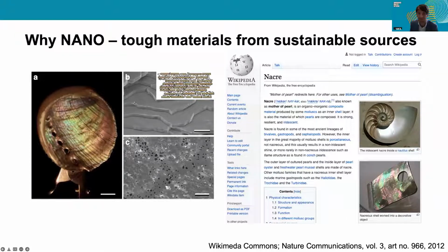So you see that you have these inorganic calcium carbonate platelets that give you basically the hardness, but then these platelets are connected in a matrix of organic matter, and this organic matter is like a glue, and provides you with the strength so that this material is not just brittle. Okay, so it's really a beautiful material to be inspired from as a materials engineer.